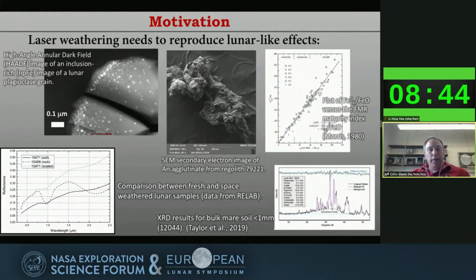All right, so in the sense of lunar space weathering, we have a number of different parameters to try and recreate with laser space weathering, and I've outlined five of them here. The first is rims that occur on minerals, and those rims, in this case an inclusion-rich rim, often have nanophase iron in them. And with short pulse lasers, we can recreate that feature.